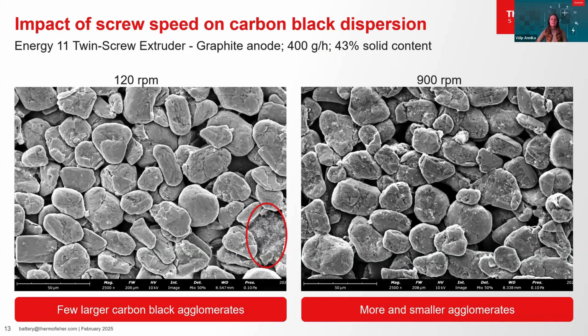These SEM images of graphite anodes mixed with a twin screw mixer at 120 RPM and 900 RPM screw speed respectively show carbon black agglomerates on the larger graphite particle flakes. Higher screw speed and thereby higher shear impact result here in a higher amount of smaller carbon black agglomerates. Next, we see the screw speed impact on another material.